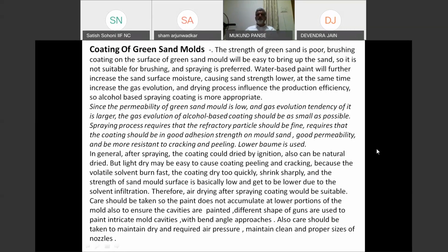Green sand should be used mostly for spray painting of alcohol-based paint, and that paint should be ignited, taking care that it doesn't accumulate at the bottom portion. Excessive paint is not there, so it will not form gases. It gives good adhesion to the mold surface. After spraying, the coating could get ignited, or it could be naturally dried. Natural drying is difficult because you will have to give a lot of time. You should ensure that there is no peeling, cracking or blistering of the coating.